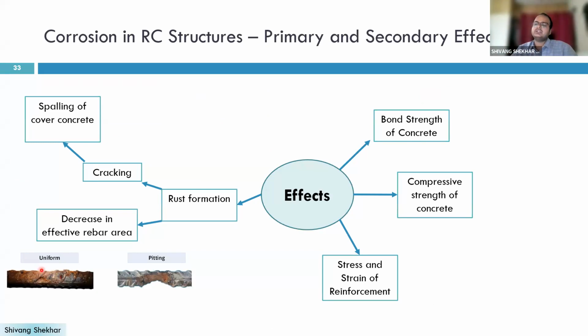You can see I have shown a corroded rebar. Now, in the case of chloride-induced corrosion, due to the spatial variability of the chloride ion, there is a corrosion called pitting corrosion. Across the length of the rebar, the corrosion is not uniform. It is non-uniform corrosion. At different locations, different pits form across the length of the rebar, and that also leads, obviously, to a reduction in cross-sectional area.